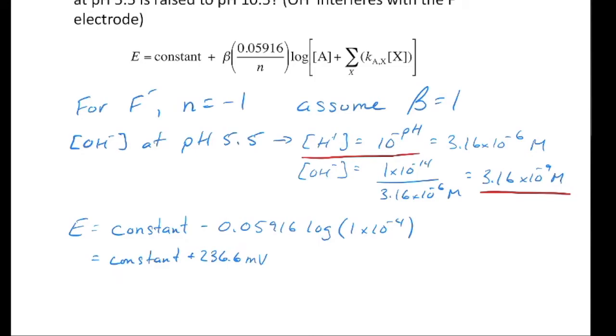So if we were to use this as the concentration of OH minus, that would go right here in our equation where X is, and we'd also have to multiply that by the selectivity coefficient of 0.1. So 0.1 times the concentration of OH minus is going to give us a number of about 3 times 10 to the minus 10. If you look at this part of the equation here, A is going to be the concentration of fluoride, so that's 1 times 10 to the minus 4. If we're adding to it 3 times 10 to the minus 10, that is really small. It's not going to add anything to our value for the concentration of F minus. So we can ignore this number.